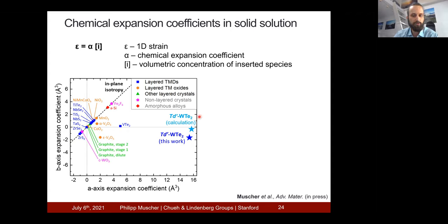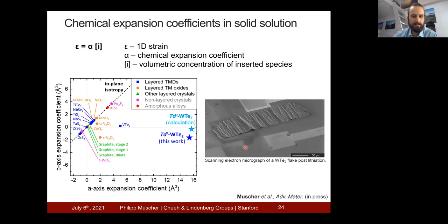Also, we were able to confirm this large expansion coefficient using density functional theory. So this is really exciting, because this shows we can actually do highly efficient electrochemical actuation, because we need only so little lithium to achieve such great expansion. And looking at this anisotropy, you can see that if you have a tungsten ditelluride flake that's stamped onto a substrate, that's adhering to a substrate, there will actually be a lot of rippling as lithium is inducing this expansion.